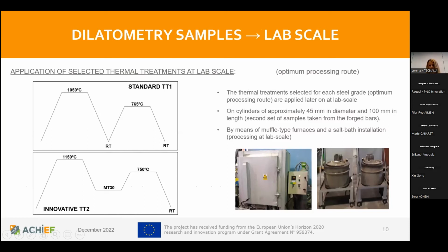In order to do so, we need lab scale samples and lab scale processing facilities. The lab scale samples used are cylinders of approximately 45 millimeters in diameter and 100 millimeters in length, which is the second set of samples taken from the forged bars. And then for lab scale processing, we use facilities such as muffle type furnaces and a salt bath installation.